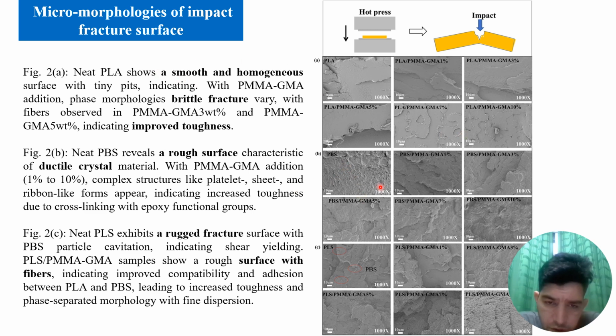After that, PBS. The PBS surface is very rough, which shows the surface is very ductile. After adding the compatibilizer, the surface changes a little bit. It looks more continuous, like some platelets, sheets, ribbons and fibers are present, which shows the increase in toughness. It is because of the epoxy functional group present in the compatibilizer reacting with the hydroxy group of PBS. Because of the reaction, many fibers are made, so the surface changes a little bit.